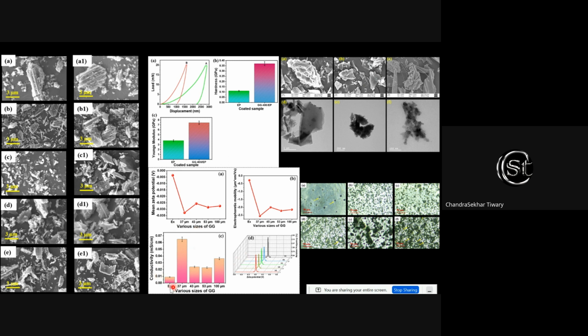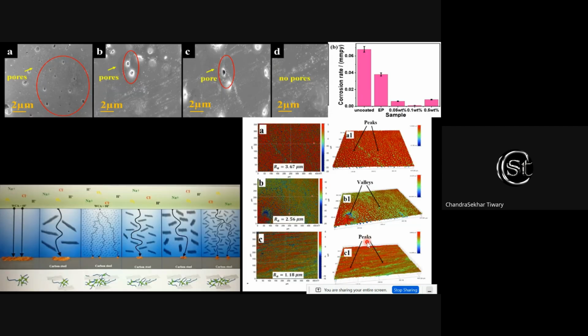The conductivity also, we can see, is lower for exfoliated graphene. Also, we look at the distribution. We can clearly see that the industrial scale epoxy has a lot of porosity. These are sub-micron level, so you can't see them, but in a scanning electron microscope we see these kinds of bubbles. Now, what do these bubbles do? Although the epoxy protects your substrate, mostly steel, if you leave it for say 10 years or beyond, these holes become a channel and help in corrosion.